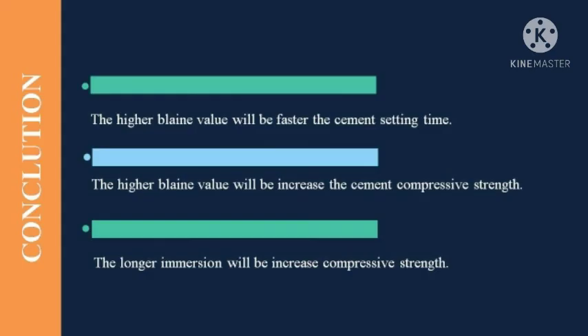From the research that has been done with the 3 problem formulations taken, it can be concluded that the higher the Blaine value, the faster the cement setting time. Second, the higher the Blaine value, the higher the cement compressive strength. And last, the longer the immersion, the higher the compressive strength.